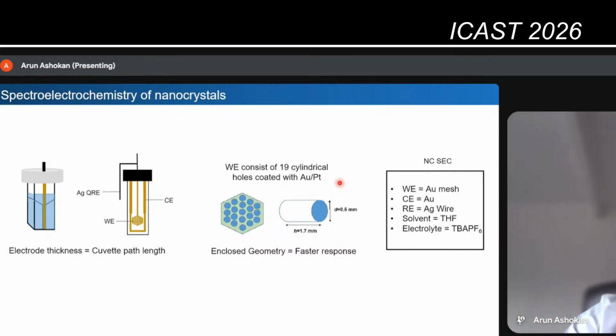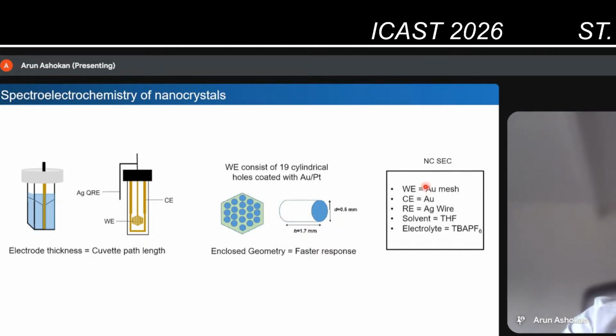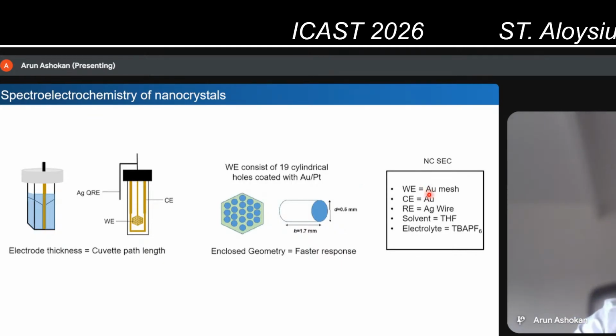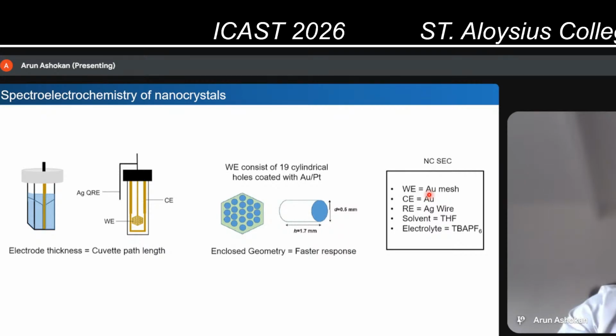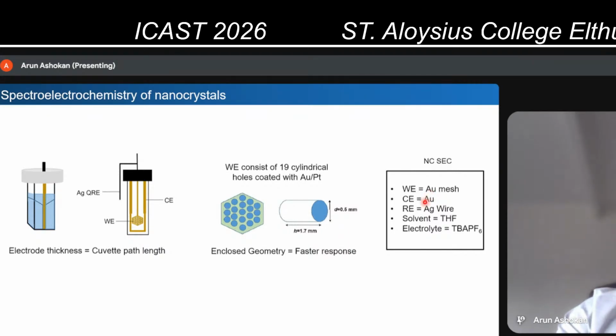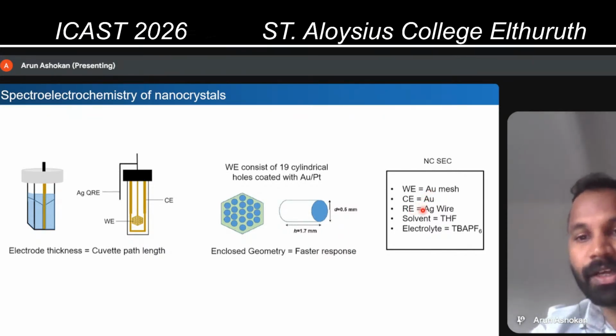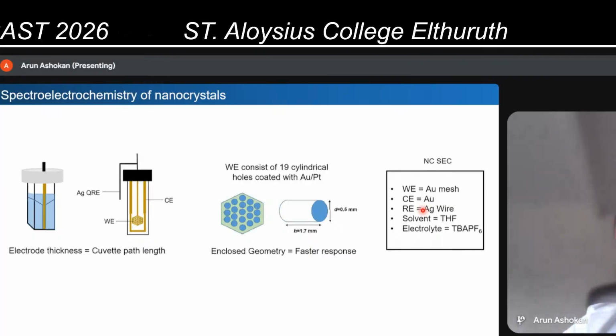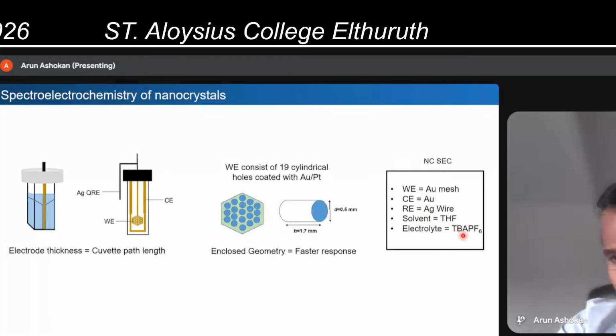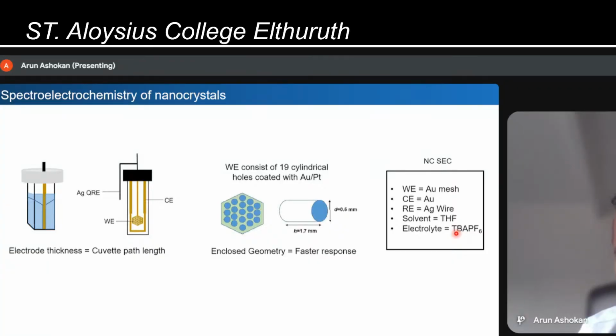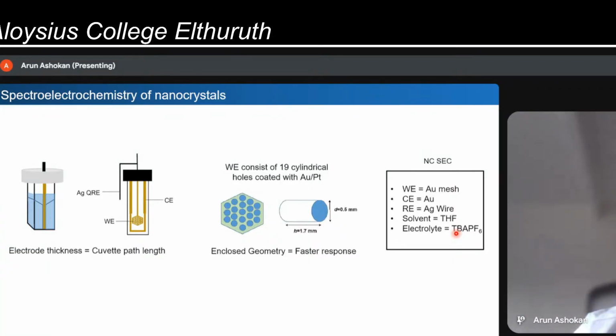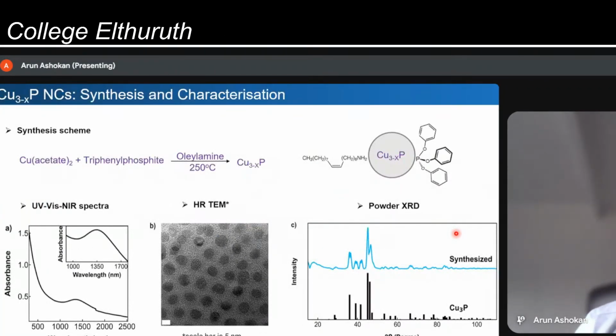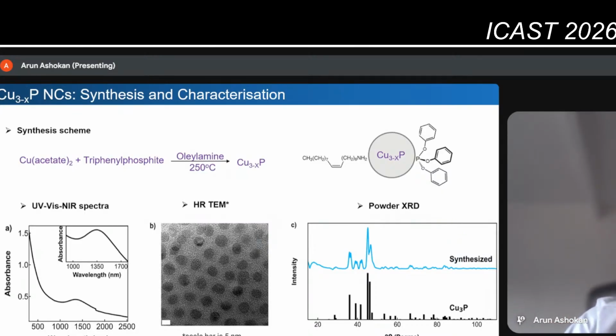In my experiments, which I'm going to tell you about now, I'll be using a gold mesh as the working electrode, gold as the counter electrode, and a silver wire as the reference electrode. All these experiments will be done in 0.1 molar tetrabutylammonium hexafluorophosphate dissolved in THF. I said I'll be doing charging of plasmonic semiconductor nanocrystals. The material I'm going to use is called copper phosphide.